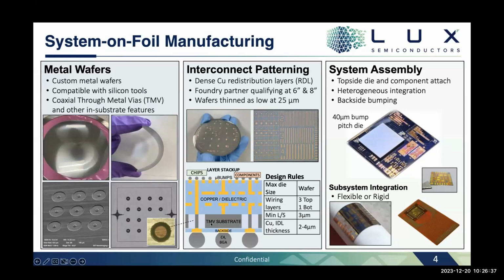However, to pattern in these components, including through metal via and others, they have to be electrically isolated from the rest of the metal substrate. And so it gets filled with dielectric in certain regions. I presume you're filling this in and then grinding it down to make it isolated. Yeah, we fill it in and then we have a backside removal process that we've developed.